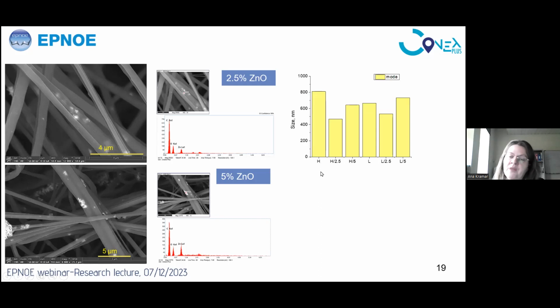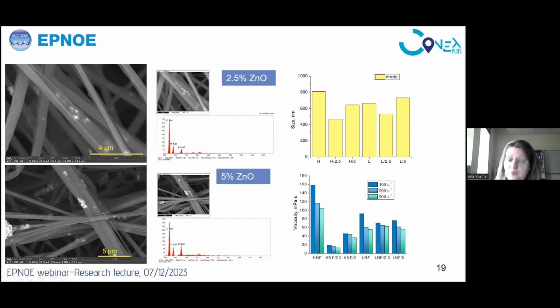When we were studying the size distribution, we saw that the average value of the size distribution is not changing significantly by changing the concentration of polymers or of nanoparticles. But we saw that the mode is significantly lower. And when we were studying the viscosity of these composite solutions, we saw that the lowest viscosity is obtained when we have a mixture of cellulose acetate and polyethylene oxide with the addition of 2.5% nanoparticles. And in fact, in this case, we obtain much, much thinner and a higher number of thinner nanofibers.